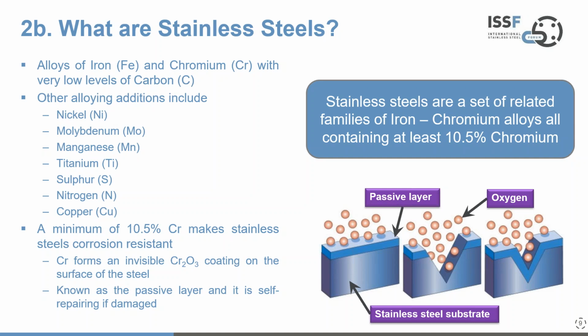Now, if you take a bit of an instrument to that surface of stainless steel, and in this case, it looks like somebody's taken an axe to it, and you damage that passive layer, all that happens within milliseconds is that passive layer heals. It's self-repairing. So the oxygen present in the atmosphere combines with the chromium and just forms a new chromium oxide layer. And that's fundamentally why stainless steels are stainless. Now, you can do things to enhance that corrosion resistance, which I'll talk a little bit about, but that's the basic principle, and there aren't other materials that behave in this way. This is a very unique feature.